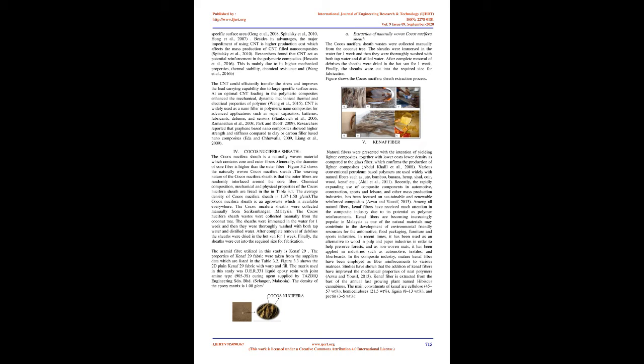Carbon nanotube, CNT, based polymeric composite. The performance of FRP composites could be improved with different nanofillers. The most commonly used nanofillers are nanoclay, carbon nanotube, CNT, silicon carbide, and carbon nanofibers. Hossain et al., 2016. Among these fillers, CNT exhibited higher strength, stiffness, aspect ratio and specific surface area. Geng et al., 2008. Spitelsky et al., 2010, Hong et al., 2007.